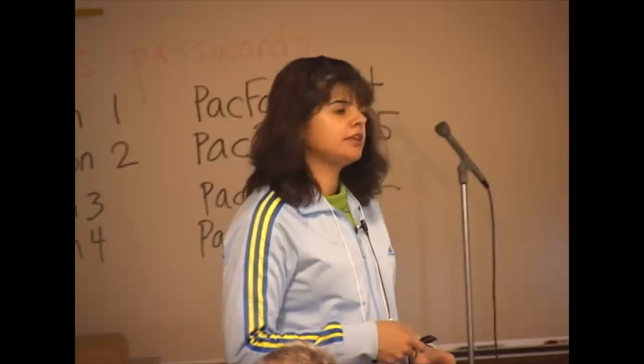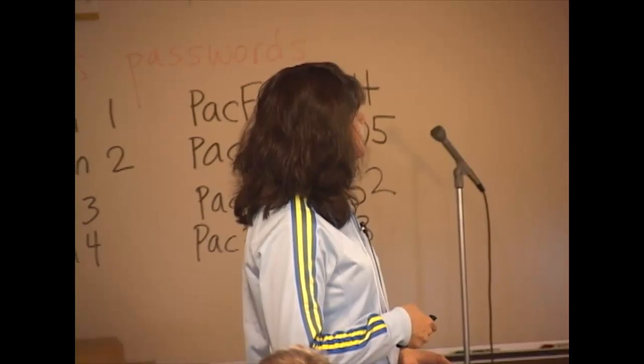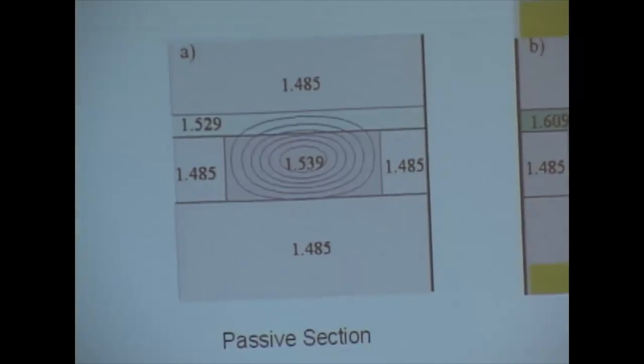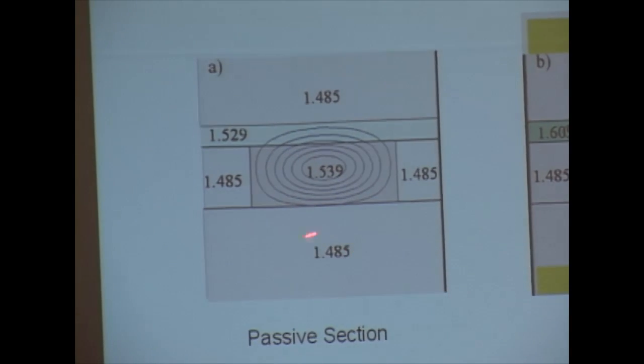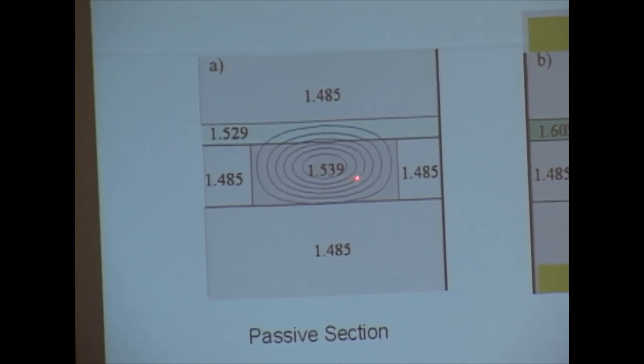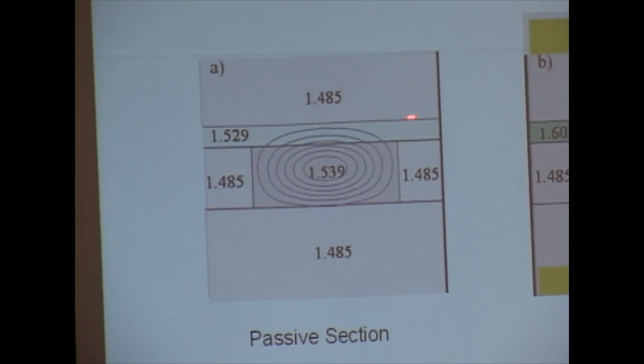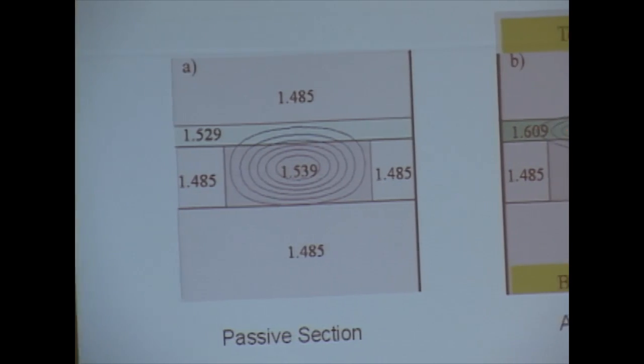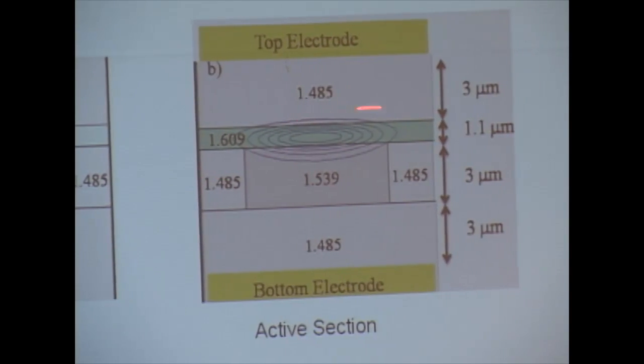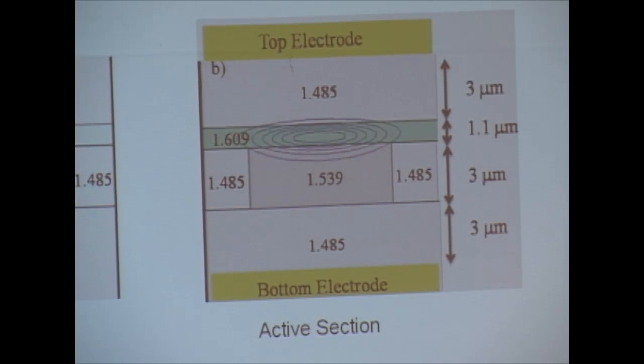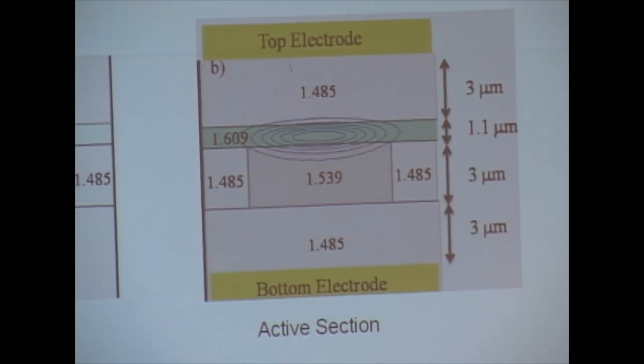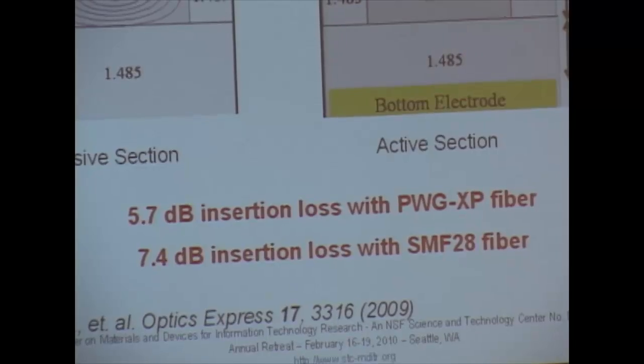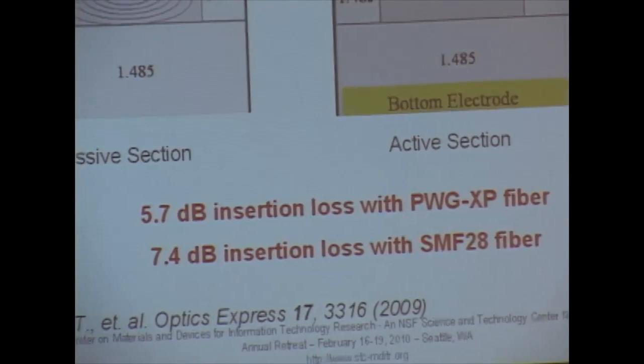So previously, we've designed high delta n strip-loaded waveguide modulators. And so it consists of 3 different layers, basically. So in the passive section, you've got the 1.485 refractive index and then 1.539 for the core. And then this is the EO polymer layer that's photo bleached, and it's 1.1 microns. And so when you don't photo bleach the polymer, the refractive index increases, and so you create a strip-loaded design, and so the light wants to go through lateral confinement into the EO polymer. And so we've seen 5.7 dB loss with a high NA fiber. But in this design, it's limited because we can't make polarization maintaining high NA fiber.